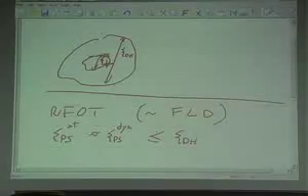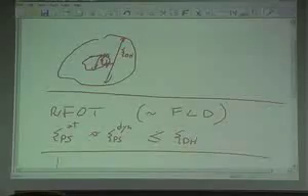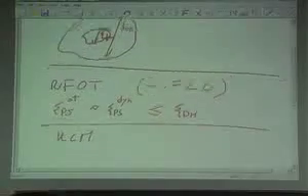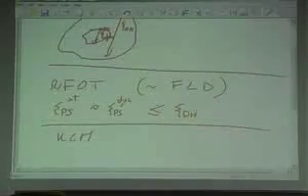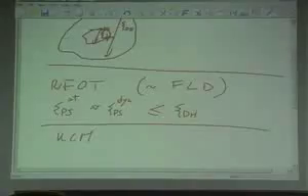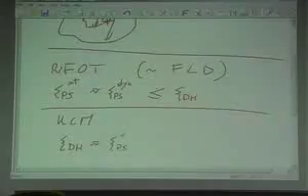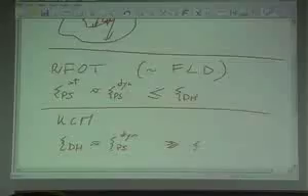So the dynamic correlation length, in general, you can think is larger than the point-to-sets. And we don't really know what the relation is. Then in kinetically constrained models, that will be discussed by Rob, I think, but I may be wrong, the Xi dynamic correlation should be equal to the Xi point-to-set dynamic, which in general should be much larger than the Xi point-to-set static. Okay?